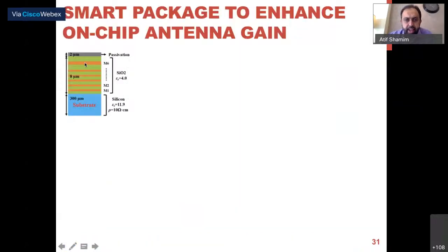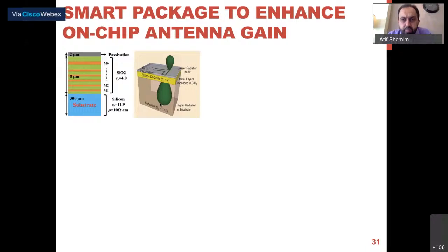So we were trying to do a project on 71 gigahertz for this. We did a CMOS process. In order to avoid the losses of the silicon substrate, we designed an artificial magnetic conductor surface. So people who are not familiar with the artificial magnetic conductor surface, this is basically an FSS structure or a high impedance surface, which is backed by a ground plane. So you have a repetitive structure, and then you have a ground plane at the bottom. What can this do? And this is showing the simulation model of this structure.